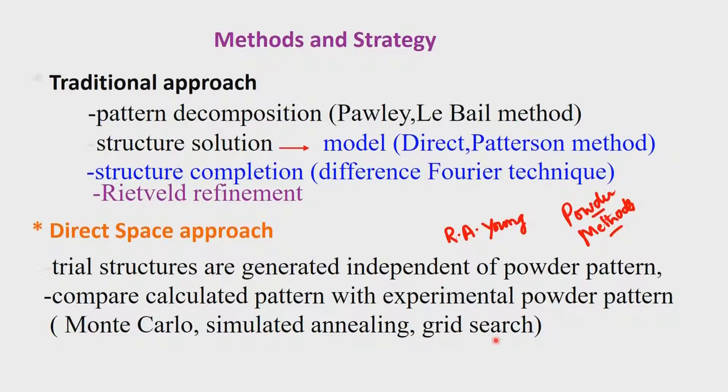These methods will allow you to give a starting model for the structure. They are based on the knowledge in the databases, so making use of database knowledge we can build a possible starting model, run it through these theoretical approaches to get to a situation where we are nearly correct in our structure, and then compare the calculated pattern with the experimental pattern and do the Rietveld refinement to solve the structure.